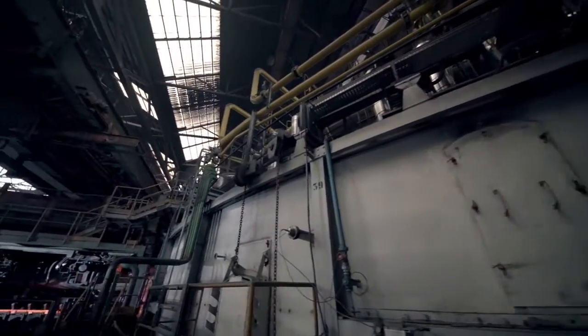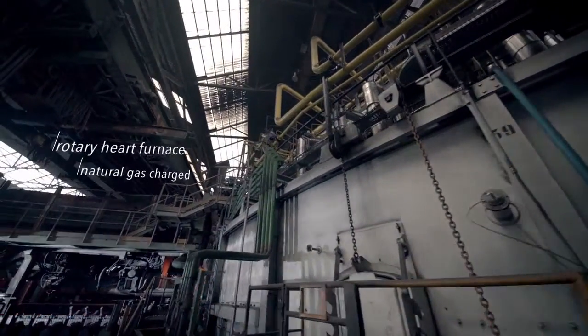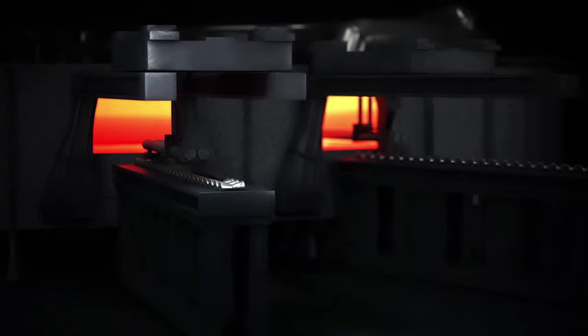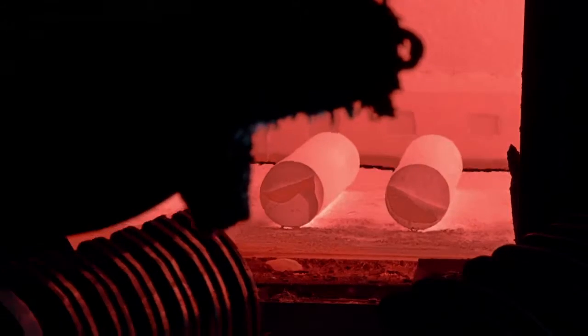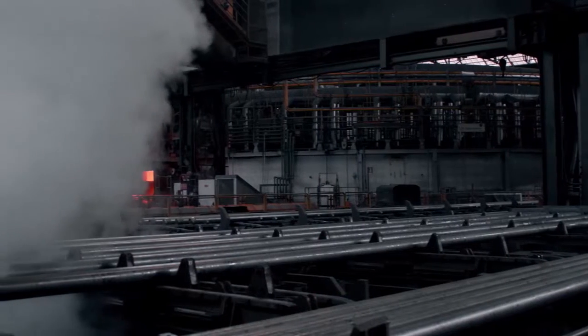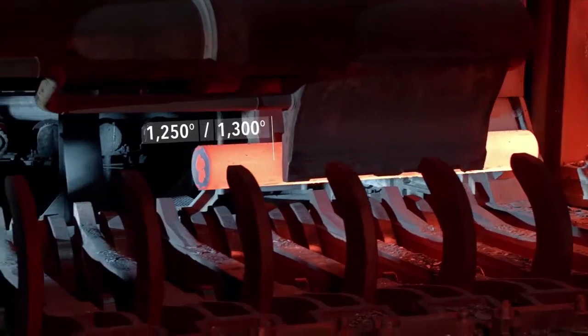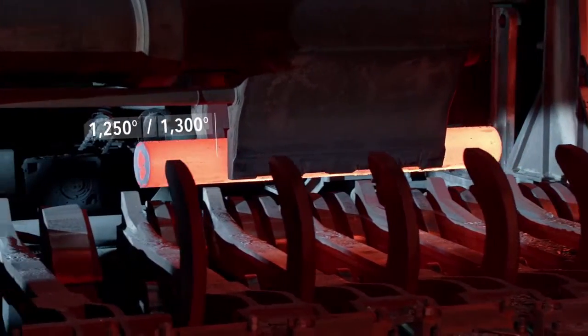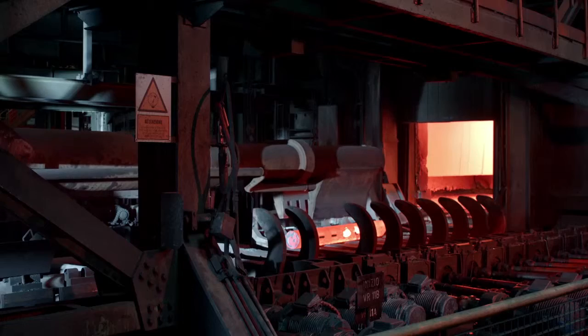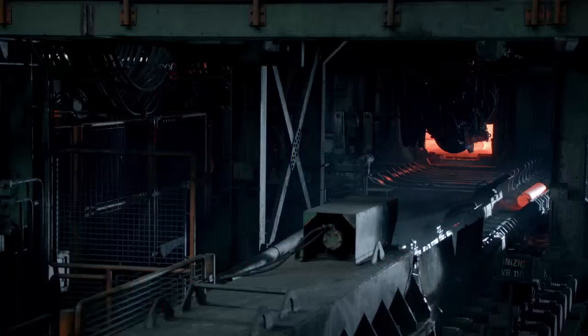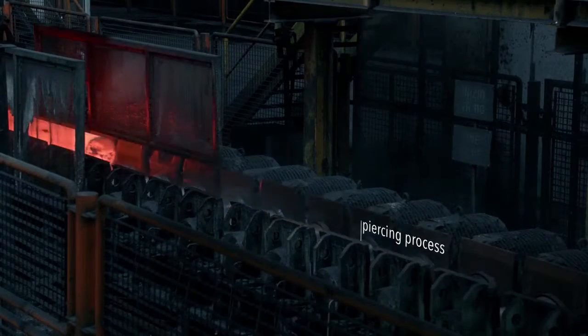These billets are loaded into a natural gas-powered rotary hearth furnace for heating. Billet sizes relate to the final tube dimension, while heating time is related to the billet size. The final billet temperature is around 1,250 to 1,300 degrees Celsius. The billets are then transferred to the hot rolling mill for piercing.